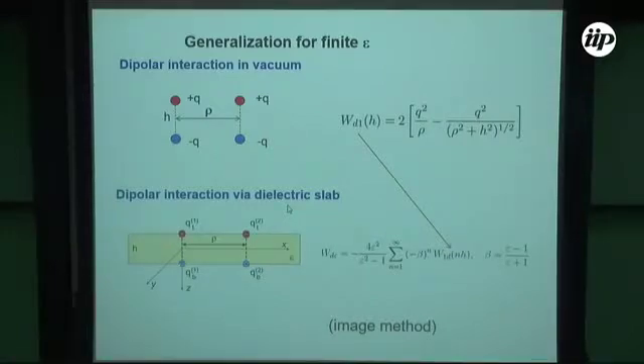If we have two dipoles in a ferroelectric slab and they interact with each other, what will be the energy of interaction? The interaction energy can be found when we have some epsilon inside. This is done in different ways, for instance, by the image method. For two dipoles with epsilon equal to 1, one can actually make a summation of this formula, because this is some kind of image method, to see what will happen if you have the dielectric slab between them. This is a purely technical electrostatic problem. It turns out that it has quite a compact solution.